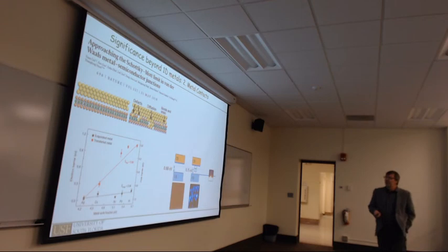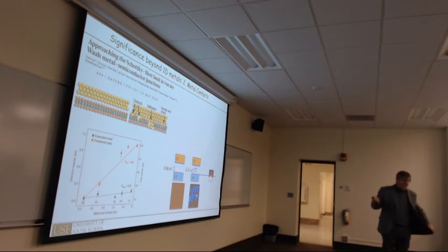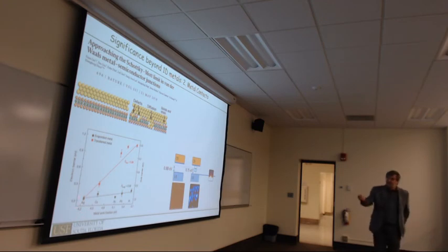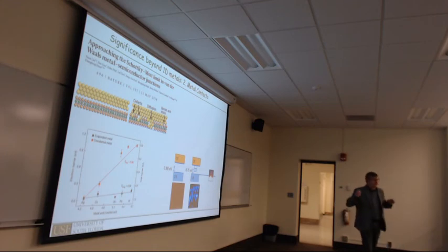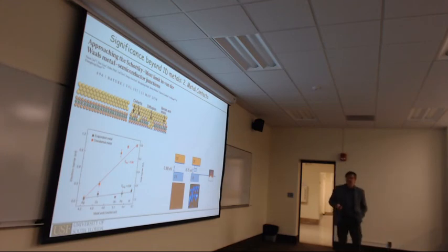There has been a recent Nature paper that looked into that, and compared metal deposited by vapor deposition and metal deposited by the transfer method. So they have a solid metal and transferred it. Only if you have the solid metal transferred, you have a nice Schottky behavior where the electron barrier scales with the work function of the metals. While if you deposit metals, then your electron barrier essentially becomes independent of the work function due to the pinning of the Fermi level by the defect states.